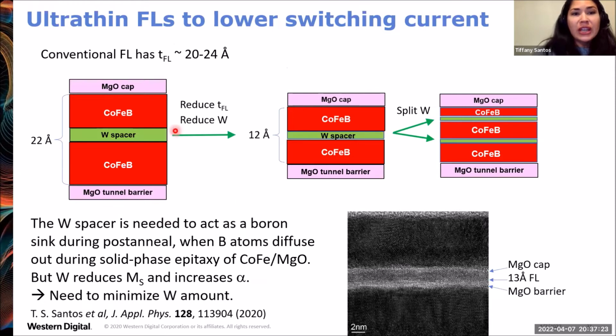So conventional free layers have a thickness over 20 angstroms. The free layer structure is mainly cobalt iron boron, and it's shown here on top of the MgO tunnel barrier and with an MgO cap on the top. And inserted somewhere in the middle is a heavy non-magnetic metal, tungsten in our case here. The tungsten is needed to act as a place for the boron atoms to go during the post-anneal process. You want the boron atoms to diffuse to this tungsten layer rather than be anywhere close to your cobalt iron MgO interface that's needed for high TMR.